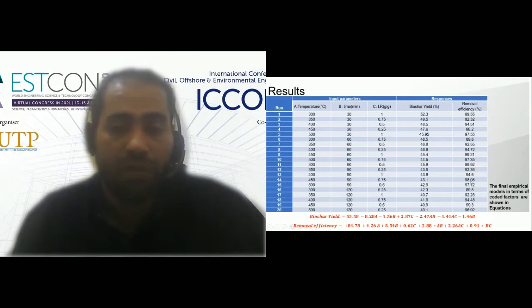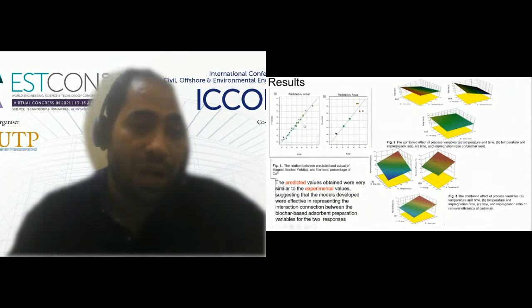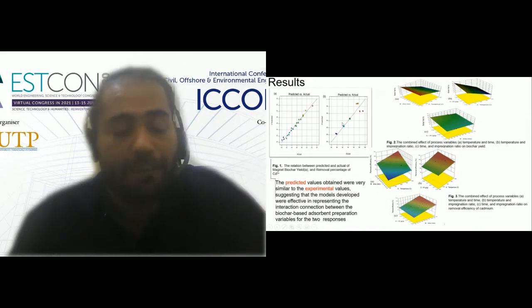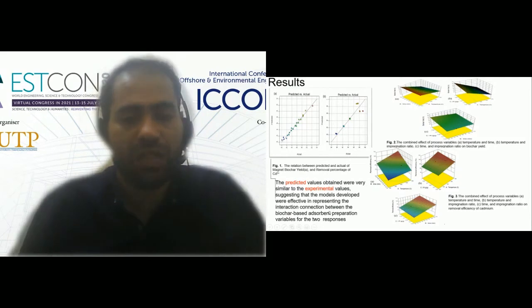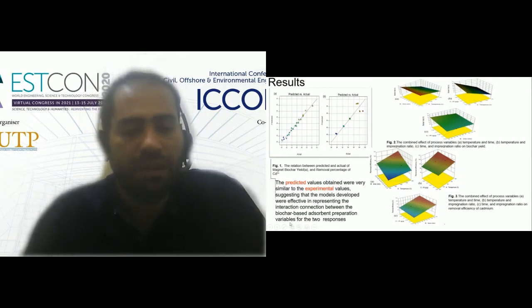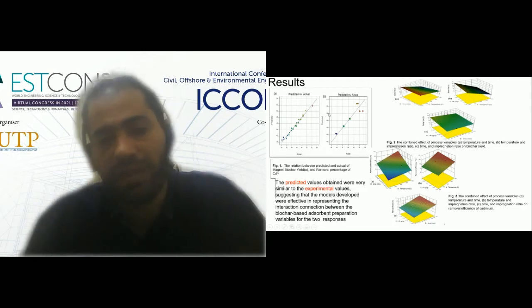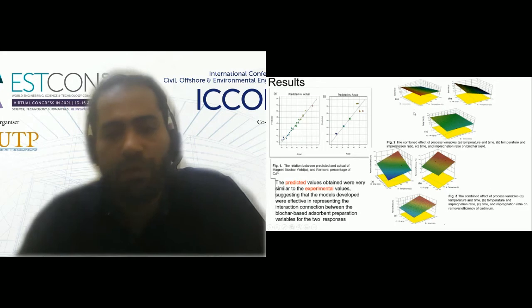We get the model from the CCD, the Central Composite Design. Now we get the results. As you can see here, the predicted value versus actual value, the relation between predicted and actual values of the response parameters, biochar yield and removal efficiency. The predicted values obtained were very similar to the experimental values, suggesting that the models developed were effective in representing the interaction between biochar-based adsorbent preparation variables for the two responses. We also have the combined effect of process variables.